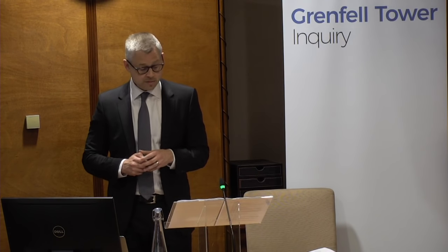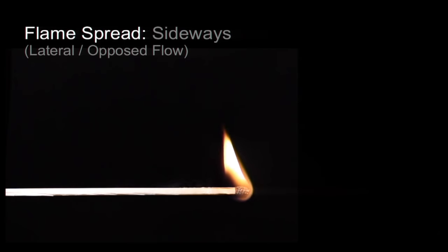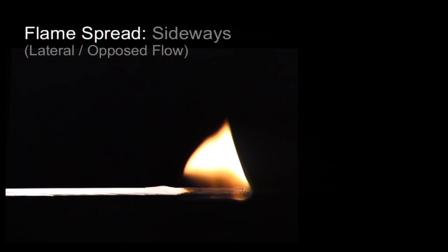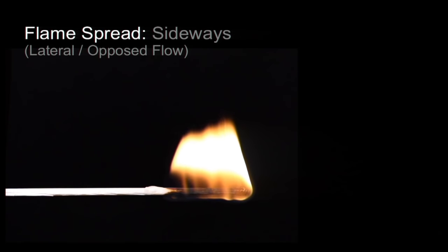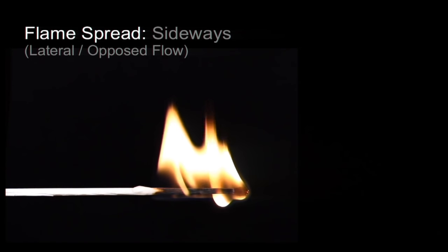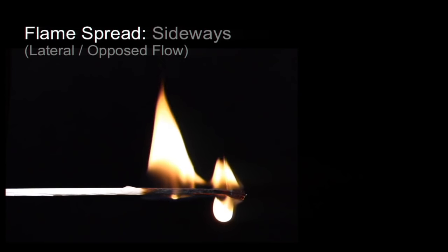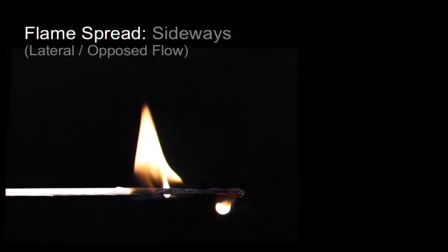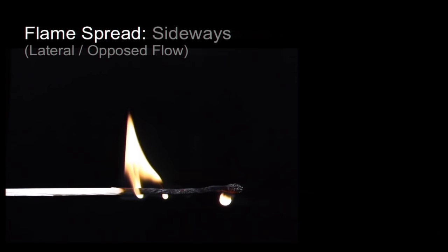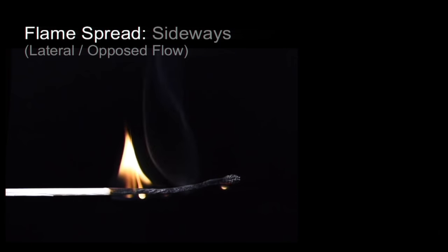In this case, the rate at which the pyrolysis front advances is approximately equal to the rate at which the solid fuel is consumed, as evidenced by a steady movement of the flame from right to left and a flame with a reasonably uniform size. And I'll show this here. And that flame just continues to the left and off the screen.